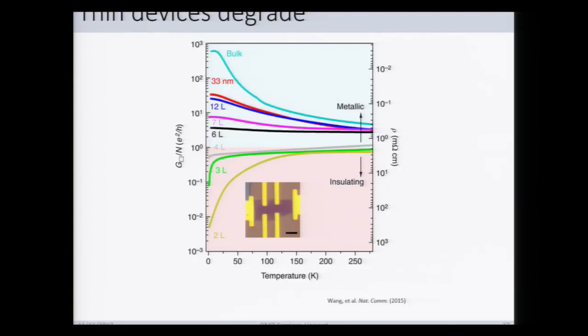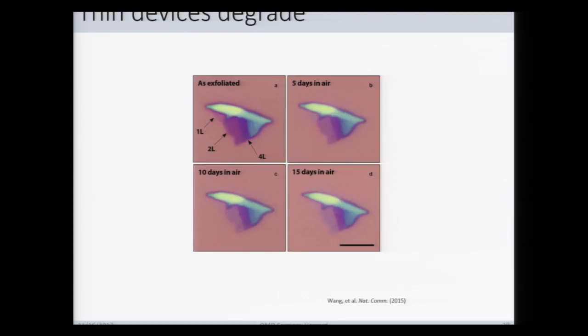Now, you might say, OK, well, didn't you want an insulator in the first place? And the answer is yes, but not like this. These states are not topologically insulating. This is just due to chemical reactivity and oxidation. Okay, so you can see this a little bit more visibly if you take an as-exfoliated crystal and take an optical microscopy image. Here is the background in pink, and then you have this monolayer region, this bilayer region. You wait a few days, and you see that, OK, this has almost completely disappeared. This has gotten fainter, and this has gotten fainter. So you can see that actually this is changing over time, and that's not what you want.